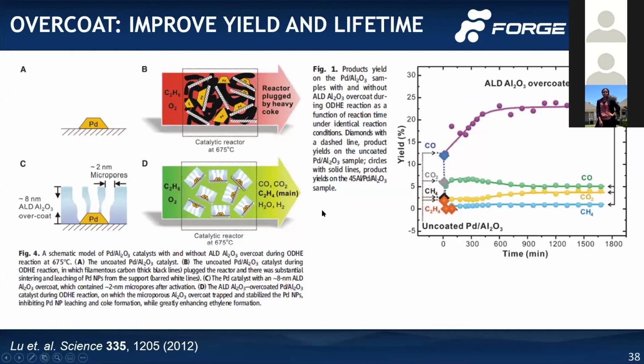So another example with overcoats here, this study from 2012. At Forge Nano, we're actually doing similar work to this. You have a palladium catalyst, then an overcoat, again, of alumina. They make these micropores by cracking the overcoat afterwards to allow exposure to the catalyst. This is oxidative dehydrogenation of ethane.